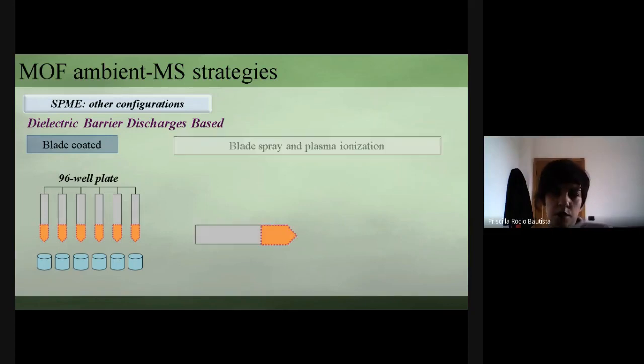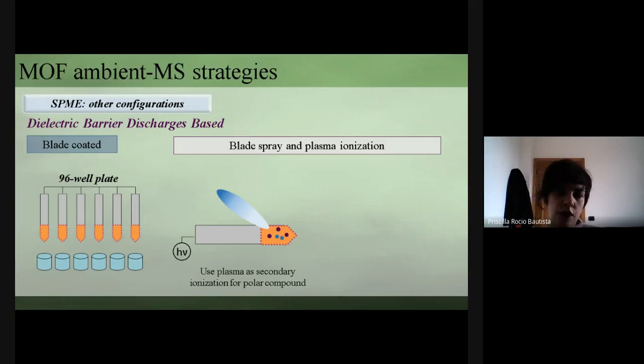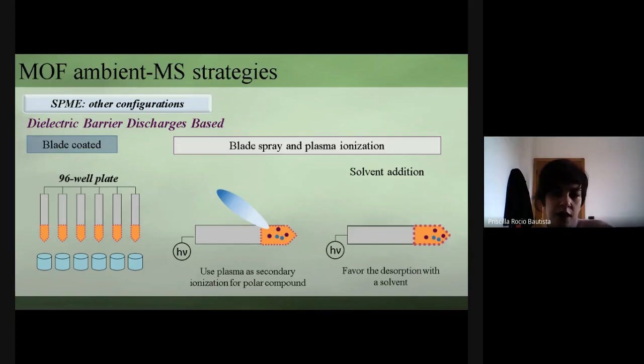For blades based on MOF, we propose the combination of blade spray and plasma ionization. As in the previous extraction proposed, the target analytes are retained in the MOF sorbent, but in this procedure, the blade is connected to a voltage to generate a spray. However, probably the ionization is not enough for molecules with certain polarity, therefore using a plasma as secondary ionization could be a good option. In this scheme, we will also study the possibility of increasing the desorption and ionization with the addition of organic solvent.